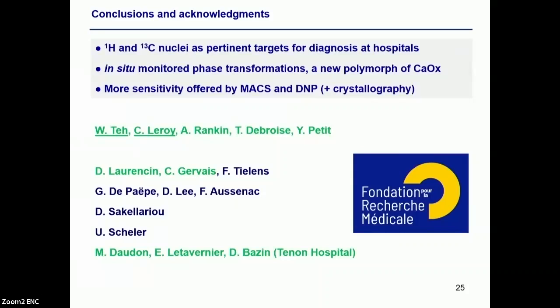Actually, can I follow up? You showed that there was a capacitor at the end of that. How do you balance that in the rotor? You have to be very, very precise about the quantity of soldering you put and so on. But I have to confess that my student, Winshin Te, has gold in the hand. I don't know if I can translate it like this, but she's preparing 10 microcoils, and the 10 microcoils spin, I would say, at 5 kilohertz, no problem. Above, sometimes we break the microcoils. The diameter of the wire is 35 micrometers, so it's less than a hair. Good craftsmanship. Other questions for Christian?